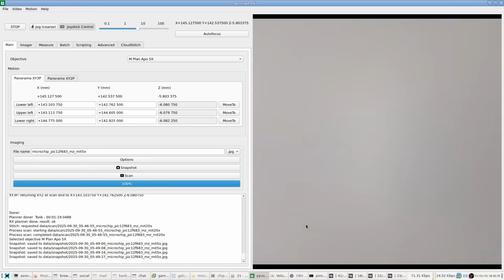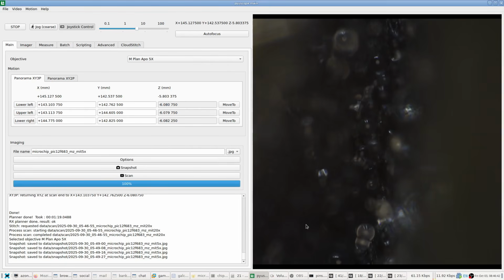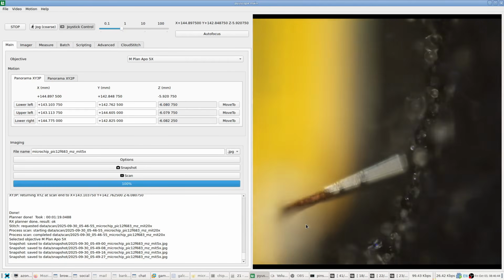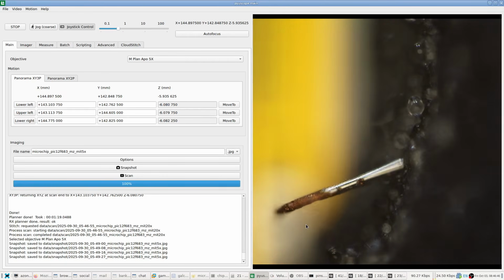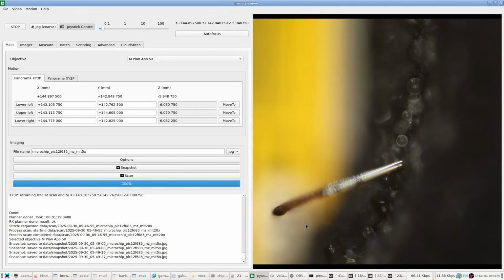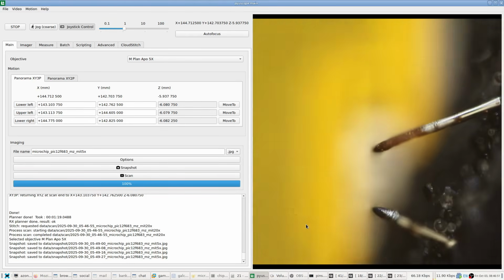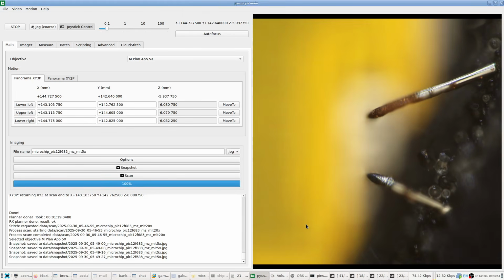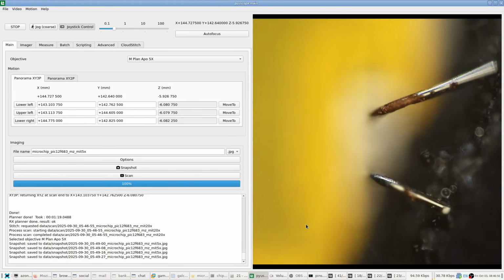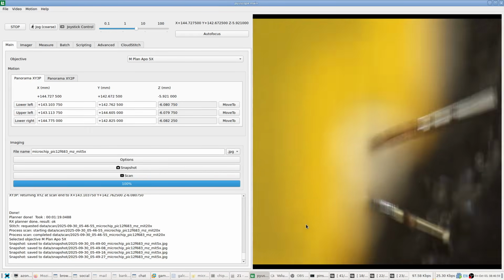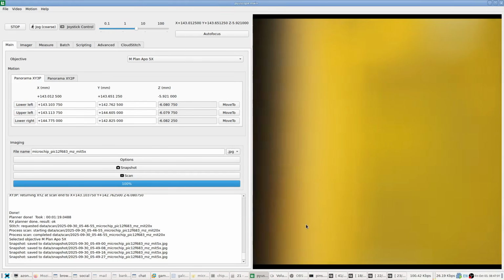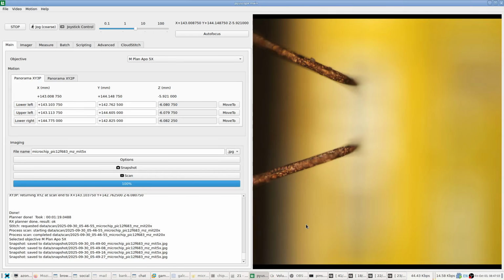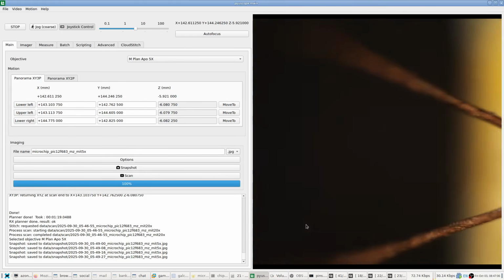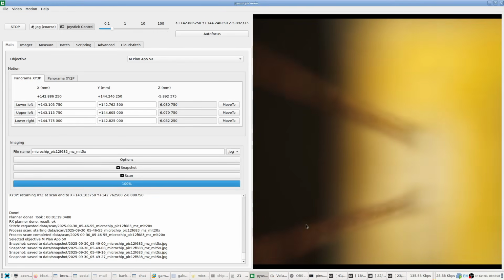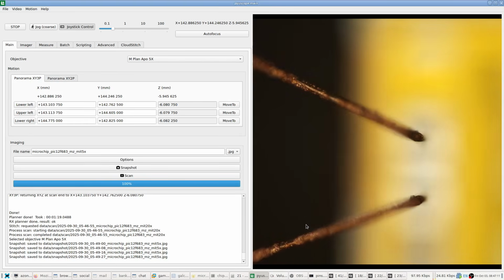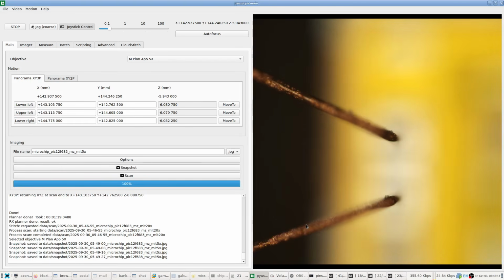Let's zoom in more, switching to the 20x objective here. We can see a little bit of the palladium coating is still intact on this wire, and then as we get a little bit further down, there are some areas sticking more out of the molding compound that are exposed with just very, very light surface corrosion, but almost nothing, or sorry, surface pitting. Any corrosion products have been washed off by the clean. One little crystal on the side of that one. But wires overall in very good shape.